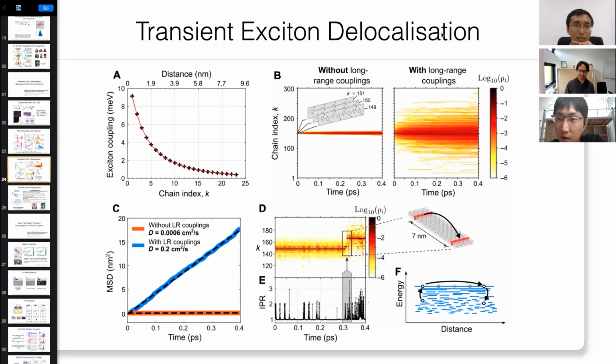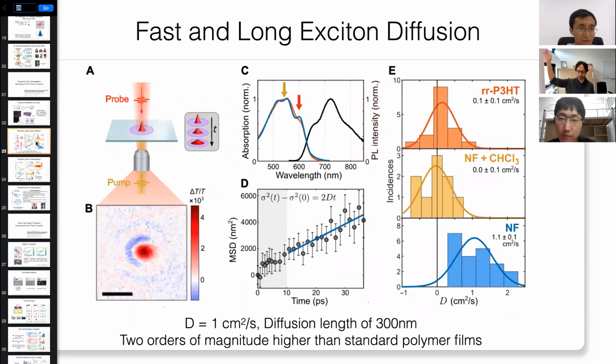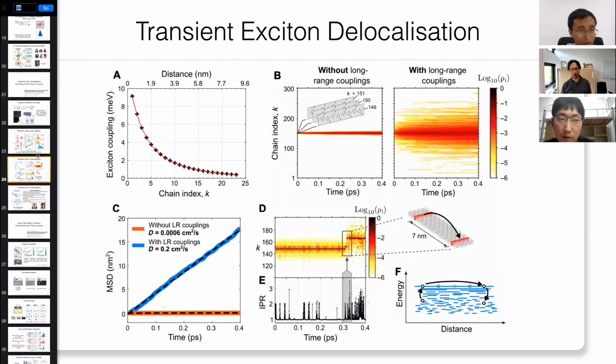Yeah, so this is a good question, and the answer is basically no, because this mechanism is happening in equilibrium. So you excite your sample with whatever photon energy you want. You can, let's say, double the band gap. You excite very high up in energy. That will rapidly cool down within a picosecond. It will cool down to the band edge, and then you can see that in this mechanism, this goes on for nanoseconds, basically, right? So these are all cooled excitons, which can then hop back up. It's an equilibrium process, more or less, or a quasi-equilibrium process. So your initial photon energy is not relevant.